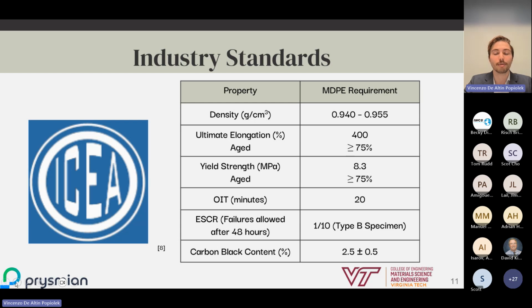The yield strength must be a minimum of 8.3 megapascals, and similarly retain at least 75% of its original performance after aging. OIT must reach 20 minutes, and ESCR is allotted 1 failure out of the 10 samples after 48 hours for a type B specimen. One thing to note for ESCR is there's 2 different types of specimens. Type A, which is slightly thicker and a slightly more strenuous test, and type B, which is slightly thinner. The type A specimens are typically used for lower modulus polymers, such as linear low density polyethylene, while the type B specimen is used for higher modulus polymers, such as MDPE and HDPE. Carbon black content was targeted at 2.5%, plus or minus 0.5%.